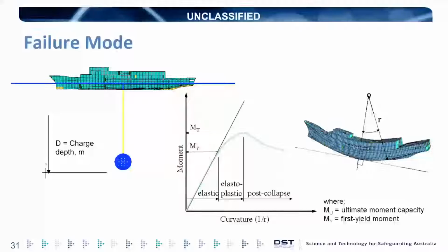Ultimate strength is just like a tensile test on a ship, except that we bend it progressively and we measure the moment. It goes through an elastic response, which is what we're designing against. Then there's an elastic-plastic response, and then it goes into collapse where you get buckling and all sorts of behaviour in the ship structure. And it occurs both in the hogging condition and the sagging condition.